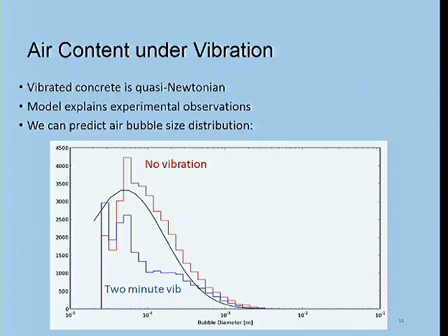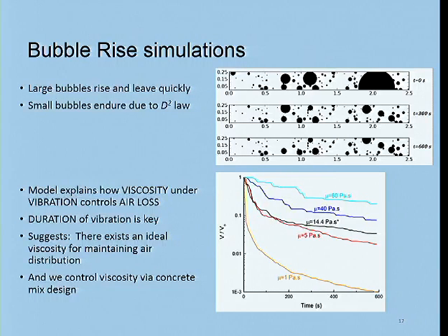It also then led us to be able to model these systems, and now we can have models that predict the no vibration case, and then we go to 2 minutes of vibration. We start with a certain distribution of air bubbles, we apply vibration, we get another distribution of air bubbles. With these kind of tools, you could design the kind of properties you need in the concrete and the kind of intended distribution of air bubbles you want to give yourself freeze-thaw protection. We were able to do simulations where we see these small air bubbles, starting with the large air bubbles. After 300 seconds, here's another picture of microstructure, and after double that length of time, even more reduction of the size that you see here.